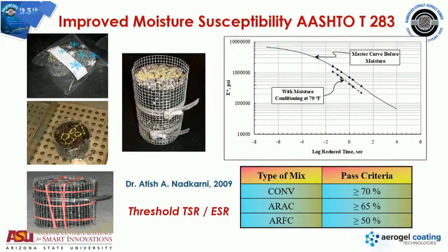But then what you see here, some cages and stuff, and you wonder, what the heck is this for, right? It's the same thing. We were doing gap-graded mixtures. If I don't protect those samples in the test procedure, they might actually change shape and deform, just because of the unconfinement. So we provided the confinement, but we wanted the moisture to go through, and that's what we have been doing in terms of evaluating moisture damage and the ESR. Again, if you search, there are some papers, publications, and reports, and so forth.